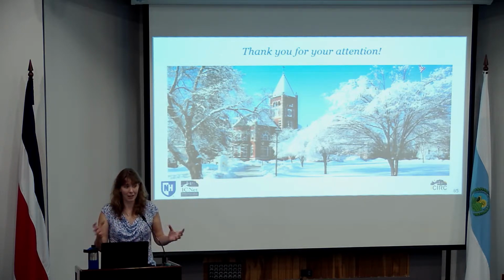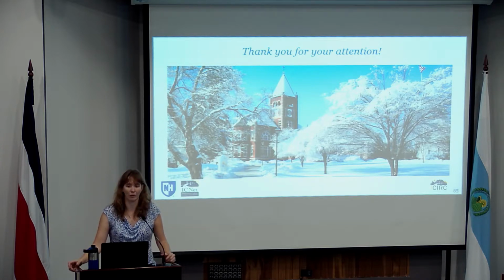Okay, and I think that the similarities that we're seeing in those aging protocols, where it's the same on the viscoelastic response, but once you get to a fracture or fatigue response it's different, tells you that there's something else going on once we start to damage that material that we've got to somehow account for. So if we're looking at the performance of the mixture, then we've got to test the mixture. There are challenges with that. It's not as easy to do, but that's the direction we feel strongly that we need to move.